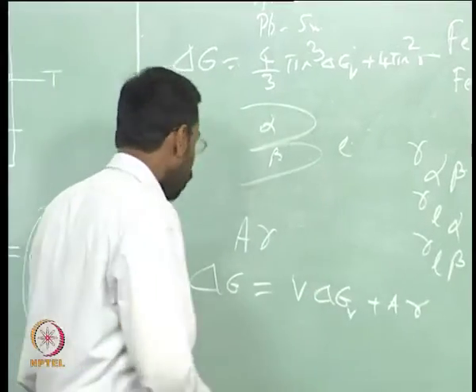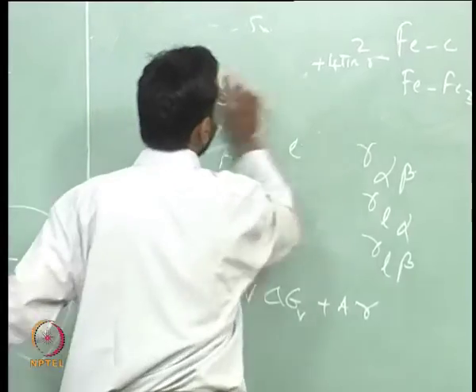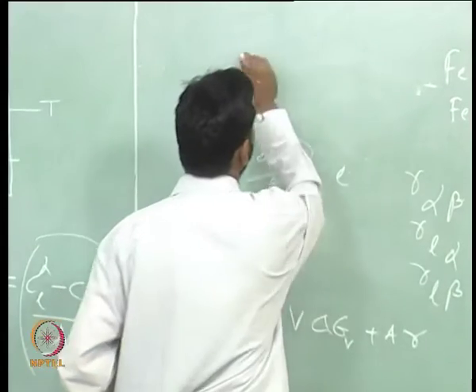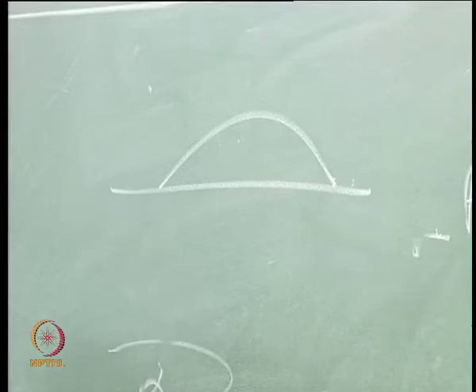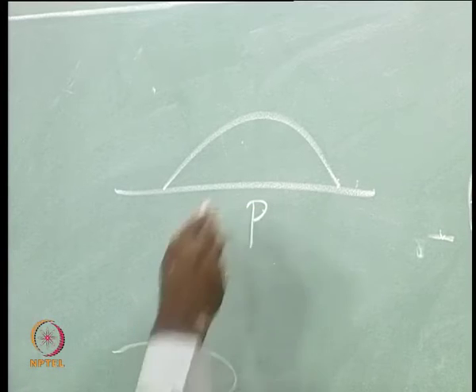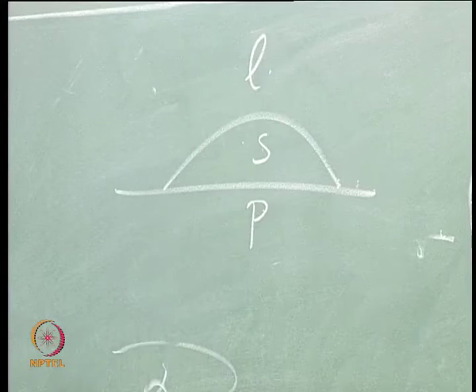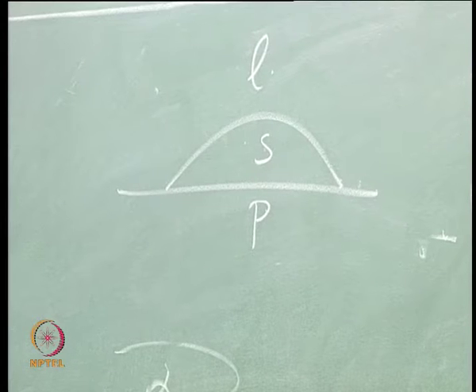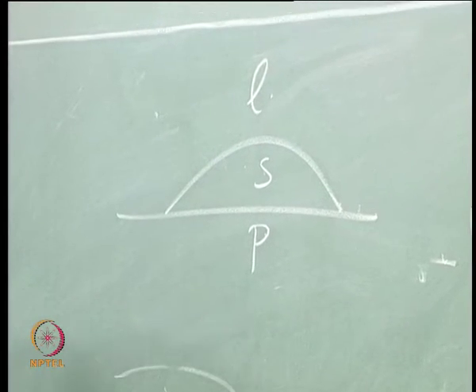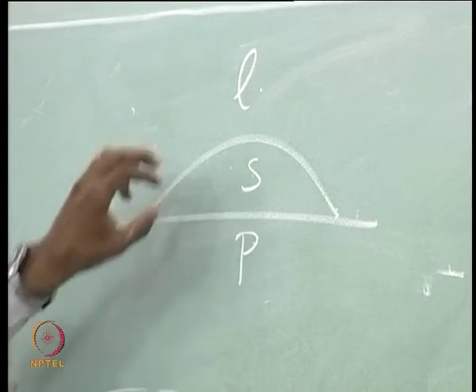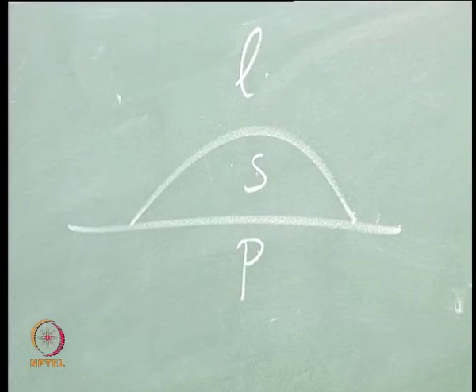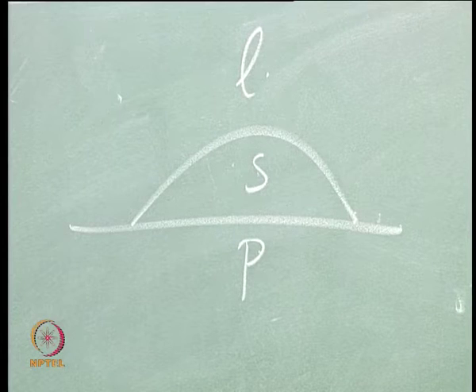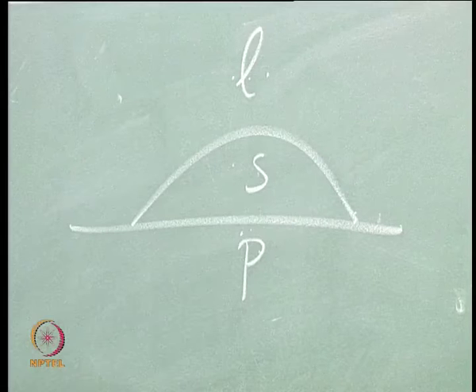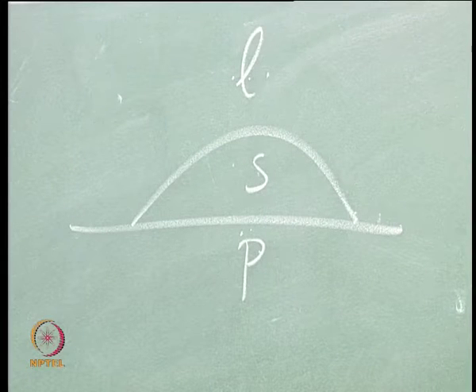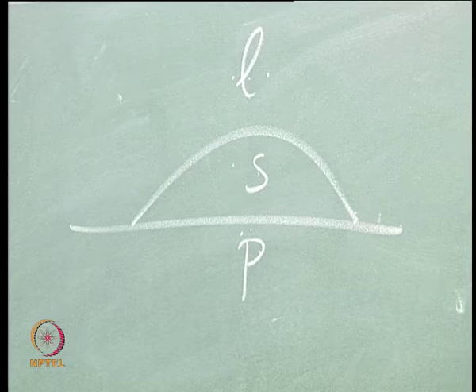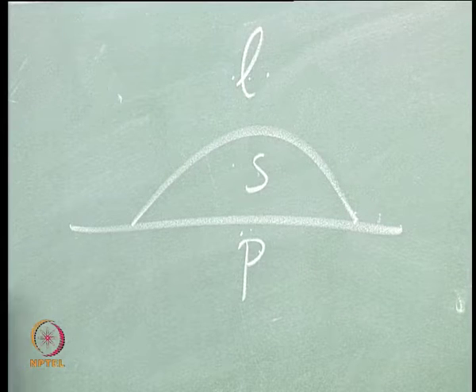Going back to heterogeneous nucleation: think of a particle here, a solid nucleating, and there is a liquid. You should know that when solidification has not taken place, if the solid has not formed, then what you have is only a particle-liquid interface. You have a particle, you have a liquid, solid has not formed on it. So you have a gamma PL.